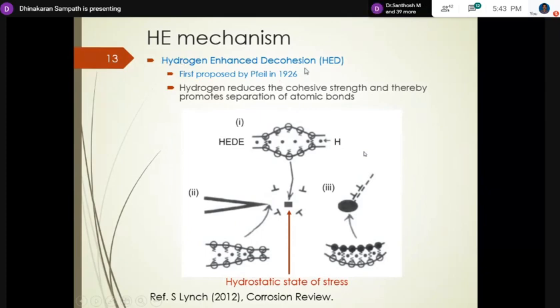So this is a very early model, hydrogen enhanced decohesion. What happens is, in the presence of hydrogen, it lowers the cohesive strength of the atomic bonds. So it just unzips and initiates a crack, which is atomic lattice distance sharp. That means it will have a very high stress intensity at this location, and it just unzips all along. That is why they call it decohesion. It just separates. And in the case of a crack, as I told, the hydrogen doesn't accumulate at the very tip of the crack, but some distance ahead of the crack, because the hydrostatic state of stress is maximum at that point. That is where hydrogen goes and sits, because of the expansion there, with room for more hydrogen to sit.